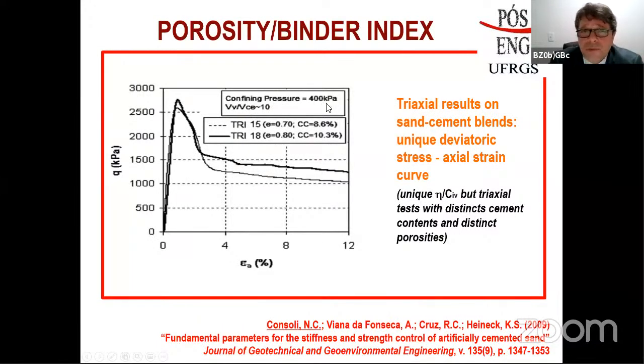In this case it was with a confining pressure of 400 kPa. We can see that the stress-strain behavior is quite similar, which means that this ratio also controls the stress-strain behavior, which is also interesting.